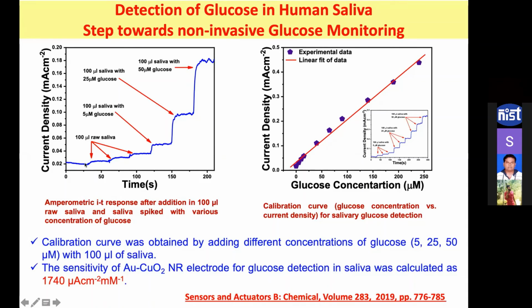So here you see, this is the raw saliva. We added 100 micromoles, and there is a nice response. Now if we use 5 micromole glucose, here it increases. So this is 25, this is 50 micromole glucose. So this increases. That response clearly indicates that gold coated copper oxide nanorod can be used for salivary glucose detection. So here you see the calibration curve.